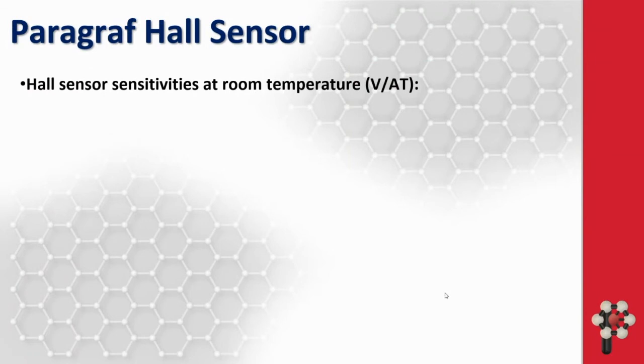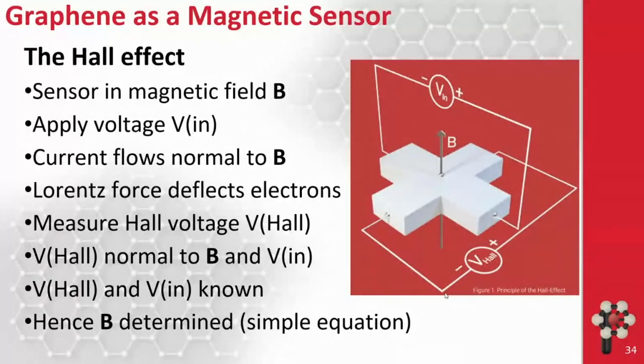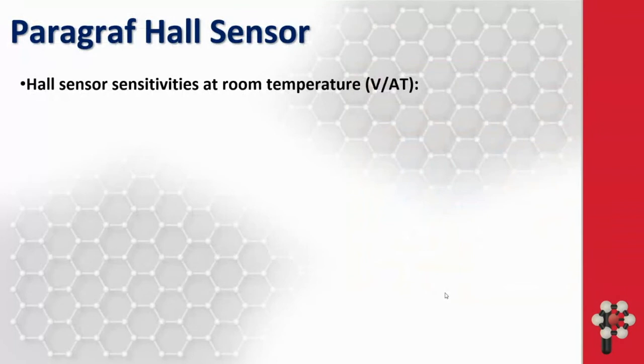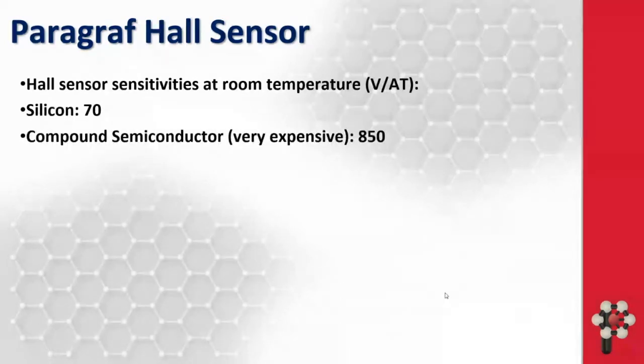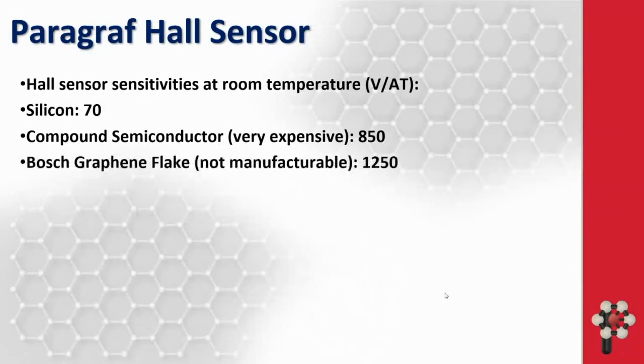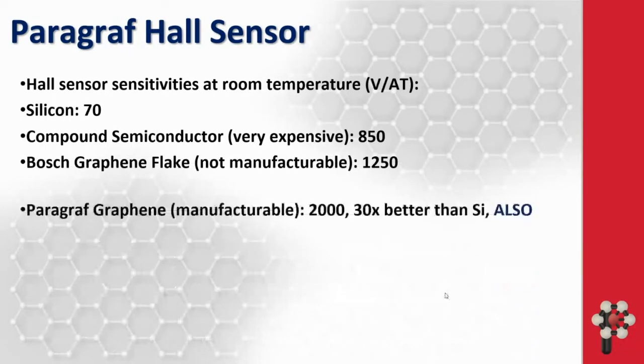So this is what we've made. The first product is a Hall sensor, and some of you may know what the Hall effect is. Otherwise, you'll find out in your lectures. But basically, you can measure magnetic fields using this, and our sensitivity compared with silicon Hall sensors, which are the standard ones, the silicon Hall sensor has a sensitivity of 70 volts per amp Tesla, which is a rather curious unit used. Compound semiconductors, these are quantum well Hall sensors, 850. The original Bosch one, if you look at their paper, it was 1250 and they couldn't manufacture it.